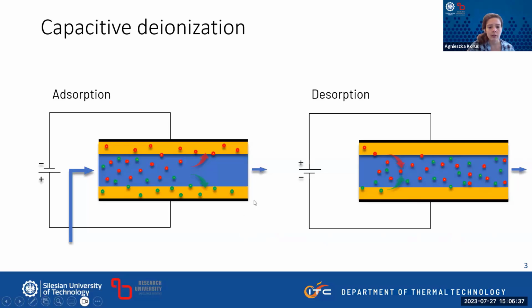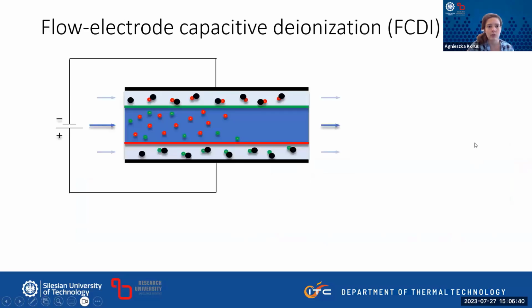Recently, there's been a twist to this method. This is the so-called flow-electrode capacitive deionization. The trick here is that instead of a solid electrode, you have a carbon suspension, carbon particles suspended in an electrolyte. So this is the so-called flow electrode, and it's flowing through a dedicated channel. So you have two separate channels for each electrode flow. And these flowing electrodes are separated from your main compartment where the water is flowing, with ion separating membranes. So here, when you charge your electrodes, the ions are just traveling through the membrane into the respective cathode and anode.